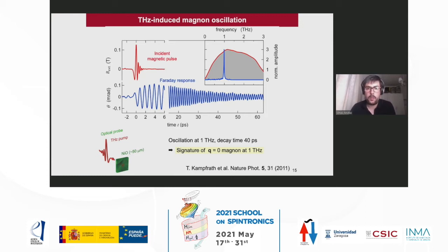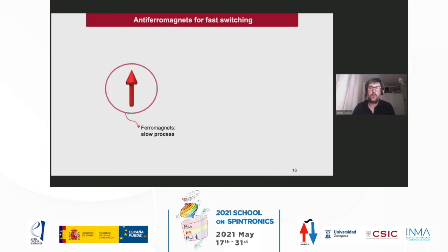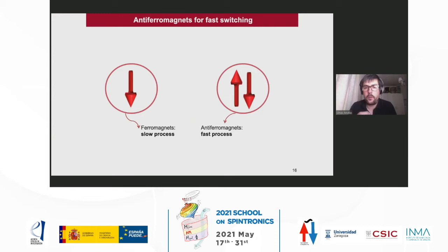So one can think that antiferromagnets are very fast, differently from ferromagnets, and so maybe we could use antiferromagnets to switch the magnetization much faster than in ferromagnets. In ferromagnets the switching process is slow, taking nanoseconds. However, since antiferromagnets have higher frequencies and picosecond timescale decay times, one would expect faster switching of magnetic states.